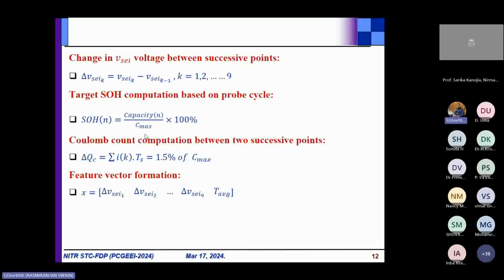Here the Coulomb count computation between two successive points has been shown. This delta QC denotes the loss in the capacity. What we have considered here is C max, the max capacity. With every 1.5% reduction of the max capacity, we have treated that as an interval, delta QC. Because of that, whatever change we notice in the delta Vsei has been considered here. The feature vector has been formed in such a way that delta Vsei points are used along with the temperature average. So these 10 feature parameters are used in the feature vector,